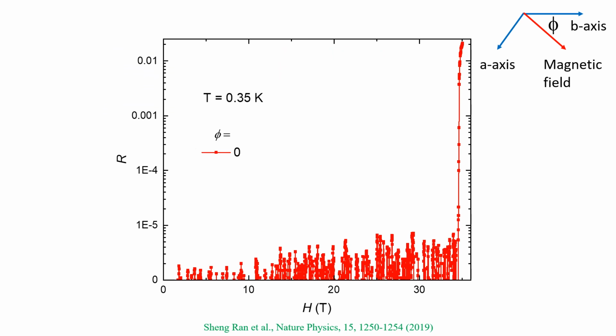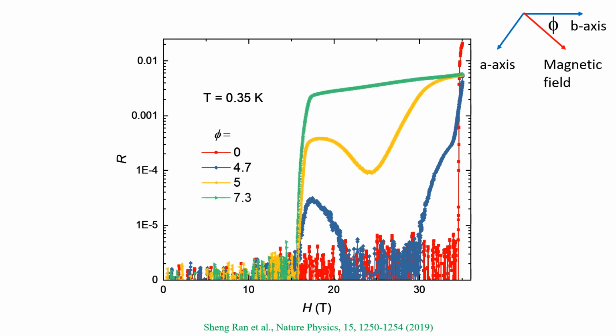Okay, I already showed you this data. This is the resistance as a function of magnetic field when the field is applied along the b-axis. But I'm showing it now on a logarithmic scale. Again, resistance is 0 all the way up to 35 Tesla, then there is a 5-order of magnitude jump. We don't have to apply the magnetic field along any one axis. As a matter of fact, we can rotate from the b-axis towards the a-axis. When we did this for some particular angle, first we saw 0 resistance, and there is a jump indicating normal state, and then it came back to 0 resistance again, indicating a superconducting phase, and then a normal state again.